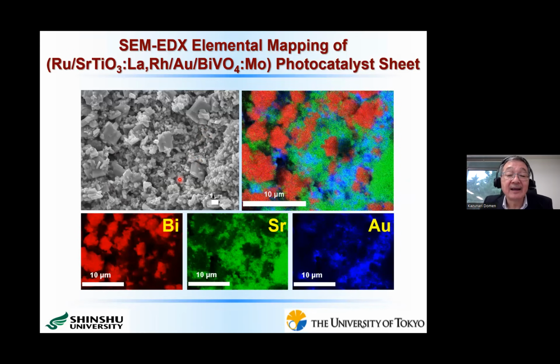Then this is a SEM image. This is a top view. As you see here, the structure is not really so well organized. This red dot indicates the molybdenum-doped bismuth vanadate for the O2 evolution photocatalyst. And this green dot indicates the lanthanum rhodium co-doped strontium titanate for hydrogen evolution. In this particular case, we use gold as a contact layer. So this is the whole structure of our photocatalyst sheet.